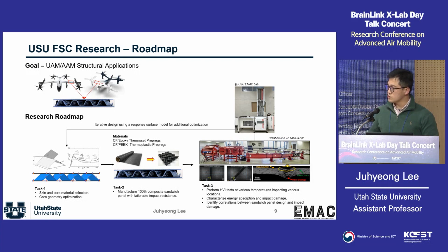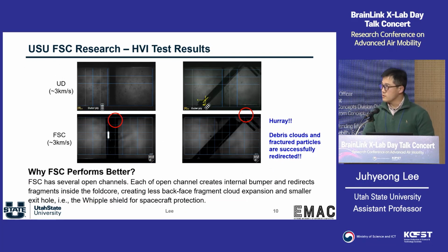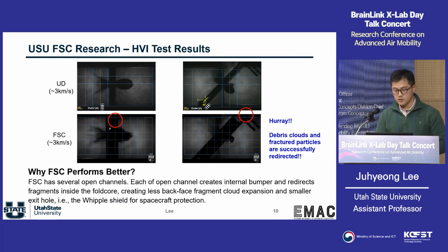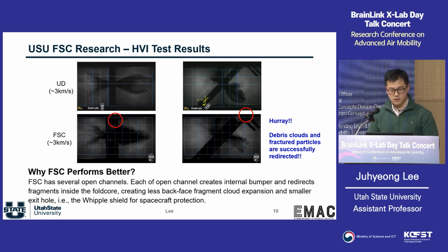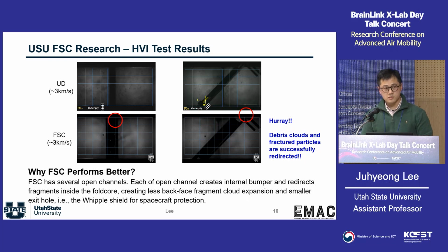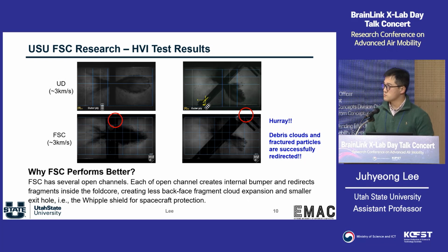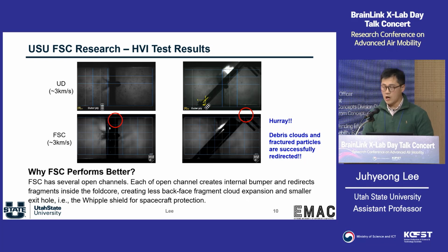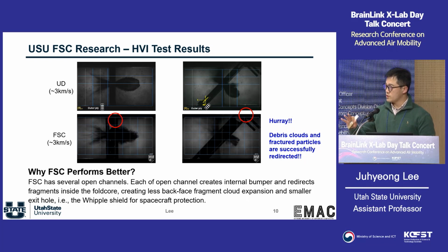Once we made all the new sandwich panels, we did a lot of low velocity impact testing and hypervelocity impact testing to measure how the structure concept behaves in different environments. This is an animation of the hypervelocity impact testing on the UD unidirectional carbon epoxy composite, the top two, and the bottom two are the carbon epoxy folded core sandwich composite. These composite panels were subjected to a 3 km per second impact, which is very, very fast. And you can see the difference in the debris cloud expansion and all kinds of particle movement. So our intention was to protect all the critical components in the backside.